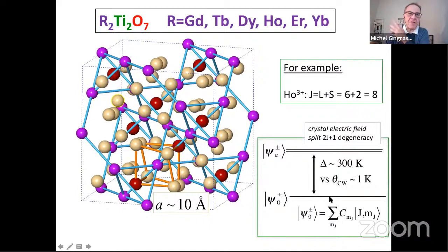And so these doublets have magnetic properties which confer to the system whether they have Ising anisotropy or XY anisotropy. I will come back to that later, but let me just say that for dysprosium and holmium, below 1 Kelvin, the magnetic response for a field along the 111 direction, along these cubic directions, is of the order of 500 times larger than perpendicular. So these systems are among the most Ising-like materials that exist in nature.